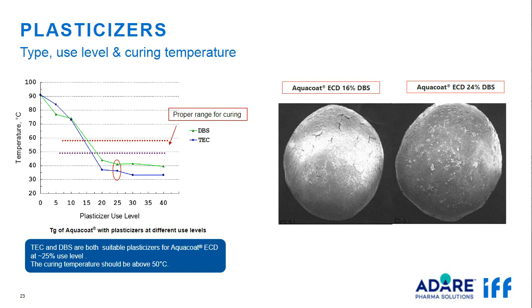The hydrophobicity of ethylcellulose can be reduced by increasing its porosity by adding suitable pore-formers. Pore-former types and level, plasticizer types and level, in addition, percent of coating or weight gain are critical formulation parameters that must be optimized to achieve desired drug release. In addition, to have a stable and robust formulation, a complete film coalescence and curing is required.